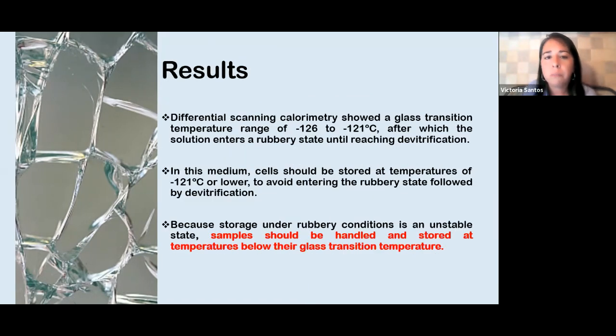Well, we also measured the TG, and it was in the range of -126 through to -121, after which, if we increase, we enter the rubbery state and then devitrify. In this medium, cells should be stored at temperatures of -121 degrees Celsius or lower. And because storage under rubbery conditions is unstable, samples should be handled and stored below their TG.